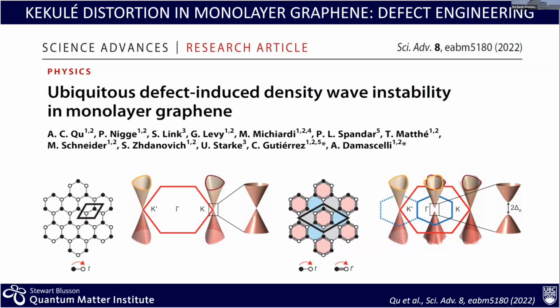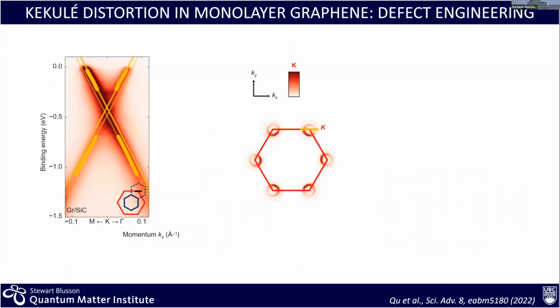So the idea is, after we have done the Landau level over the entire crystal, can we also generate a density wave order, which really has not been observed very much in this system, again over the entire crystal by small amounts of defects. The two key signatures are the folding and the gap opening. Here is the sample again, with our Dirac point at the K point. Here you already see that things don't line up very well, the upper and lower parts of the Dirac cone. This is again the effect of the mass term that gives you a bit of a gap where the Dirac point would be. But the question is what happens as we dope.